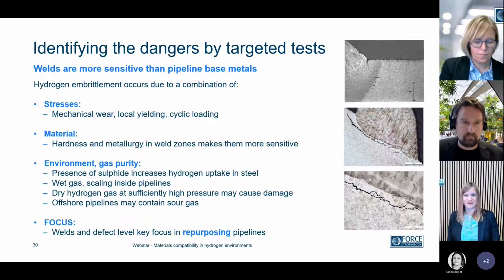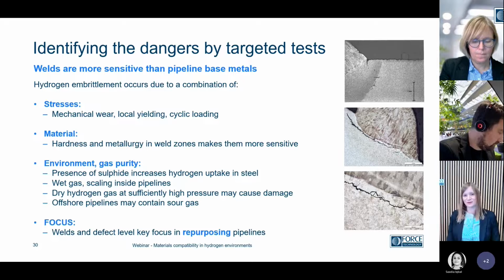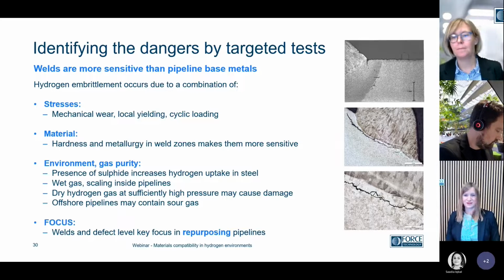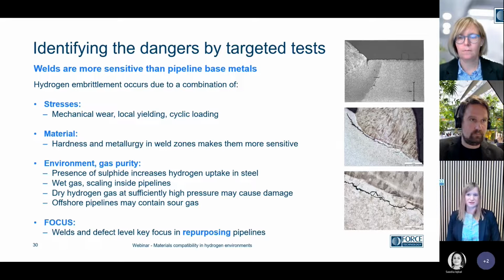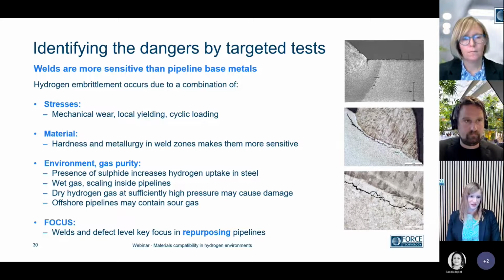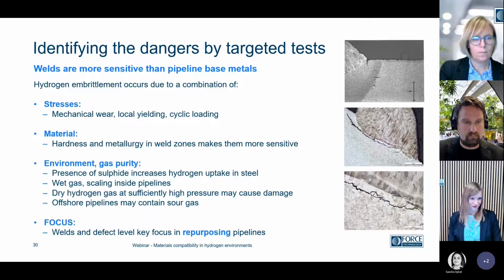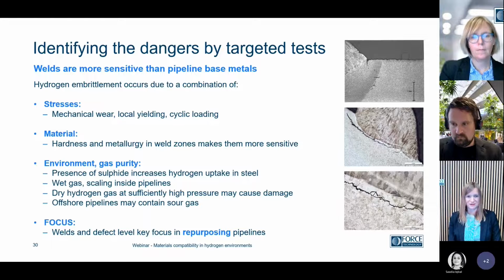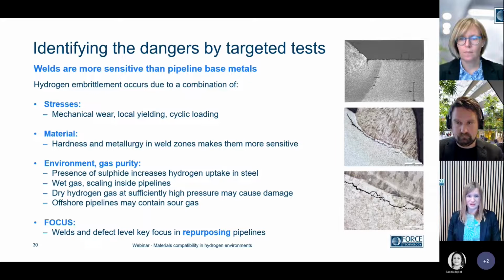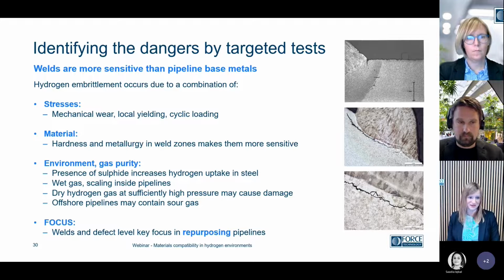One thing is these standardized small-scale specimens that can tell us a lot and sort out many parameters that can affect the test result. But testing the effect of impurities in the hydrogen backbone is relevant because we know the environment and gas purity really does affect the end result. So that was one of the first circles. We have the stress level, mechanical wear, cyclic loading in the pipelines, very important to consider, and then the material susceptibility. Here to the far right, we have cracking in weld zones because welds make the steels more susceptible to hydrogen embrittlement. So these uncertainties need to be assessed through future testing. And we believe that these welds and the defect level in general is a key focus in repurposing the pipelines.